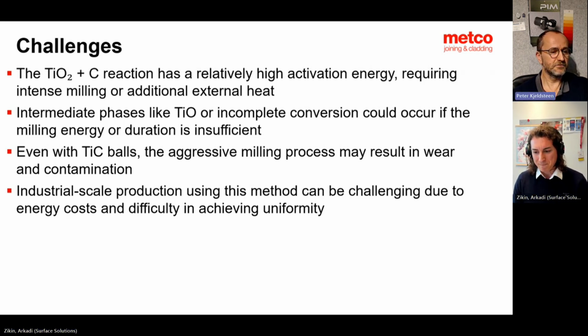How high is the yield? Are you able to transfer all the oxides to carbides? Honestly saying, I did it on a lab scale for maximum 2 kg of material. And it worked. Don't ask how many hours you ball milled. Long time. A couple of days. Very many hours. Long days. Several days? Several days.